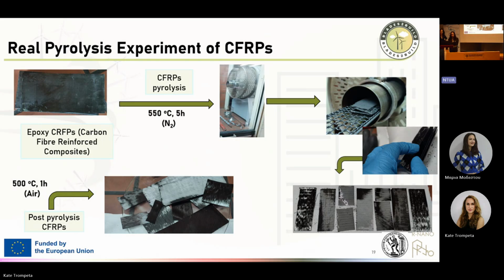Yeah, better with the microphone. Thank you. So the main concept is to identify the parameters you want to apply in order to separate all the fibers, because this process is really dependent on the volume that the specimen has. For example, if you have a few layers, then it's easier to reclaim each one of them. But if you have more thickness, then the decomposition of the resin gets trapped in the layers, so it becomes more challenging to separate. So you either have to increase the duration, or increase the temperature or the inert gas, so you remove more of the volatiles that have been produced during the process. So it really depends on the specimens that you have, and you adapt the parameters of your process.